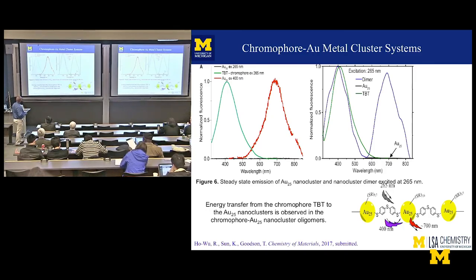There's something interesting here. If you excite the dye, you can look at the fluorescence from this gold dye oligomer. But interestingly, if you excite the gold 25 directly, you don't see any emission. So I'll say that again. If you excite the gold 25 directly at this wavelength, you don't see any emission. But if you excite the dye, you see very large emission. The emission from the dye is in this region, the emission from the gold is in this region, but there is no excitation for the gold cluster at 265. It must have had an energy transfer.